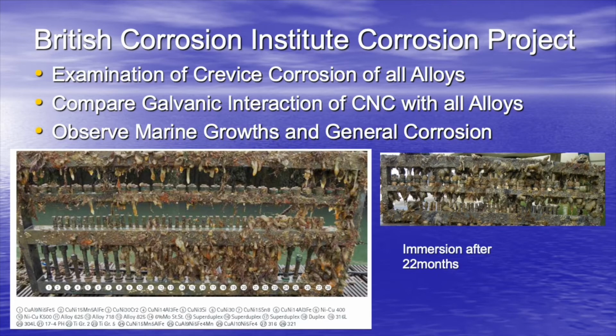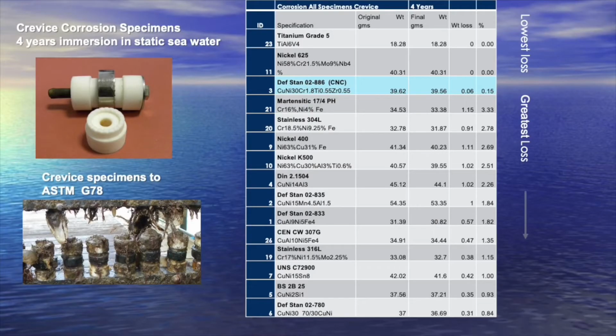You can see that there are 28 different alloys, and these pictures show the effect after 22 months of immersion. The project is a 10-year project. Now we are into our 7th year, and we have pulled 2 of the test racks up. These are the results after the first test rig was pulled up. 4 years of immersion shows that copper nickel chromium performed the best of all of the copper-based alloys.